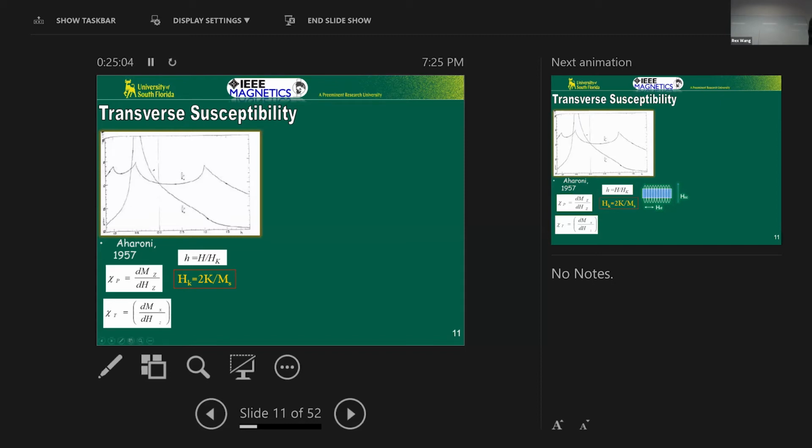And then he also showed that you can take the transverse component, which is the projection of the magnetization in the perpendicular direction. So if you look at it, it's a tensor. So he said that if you plot these two, as you go from positive high field to low field, so it's positive, and then you cross the field from saturation and change the polarity. This is with respect to the reduced field, and of course the relevant field here is the anisotropy field for the magnets.